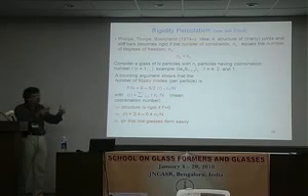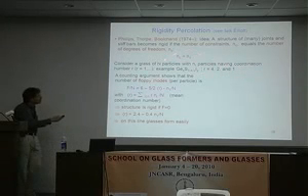Now imagine that you have a glass-forming system, that you have n particles that have different coordination numbers, that is to say they have different numbers of bonds. That's where the chemistry comes in. So if you look, for example, at germanium sulfur iodide, the germanium has 4 bonds, sulfur has 2, and iodine has only 1. And then if you use this argument, you use a mean field approach again. You say, well, on average, I have that many bonds, etc.